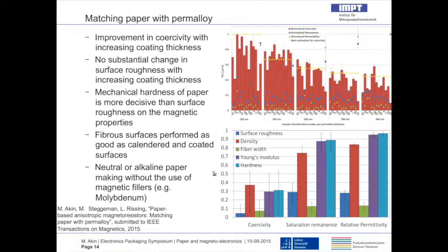We also found that the roughness of the paper is not a decisive factor for a better magnetic response. What we see here from a regression analysis is that the R square, the square of the Pearson coefficient, is smallest for the surface roughness and is largest for hardness and Young's modulus, which are the mechanical properties, basically impacting the relative permittivity, saturation remnants, and coercivity.